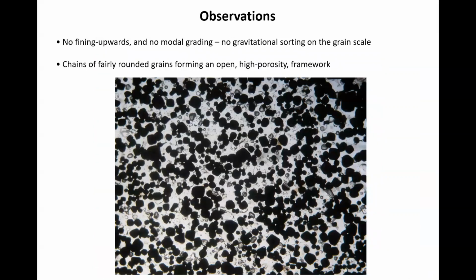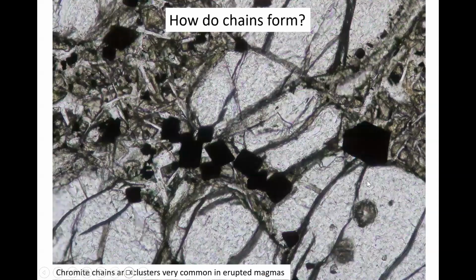And we've heard a lot about this. You can see these chains of fairly rounded grains, which form an open, extremely high porosity framework. So the porosity can be up to 60% in some parts of the layers. You can see these chains of grains here. There's another chain there, and then there. It's very striking, really remarkable when you see these open chains. So we need to address all of that.